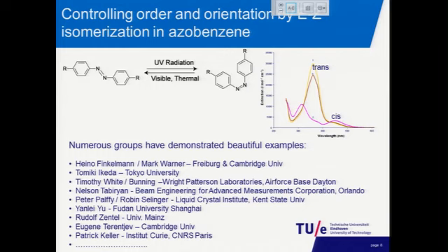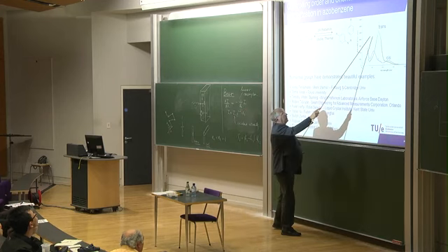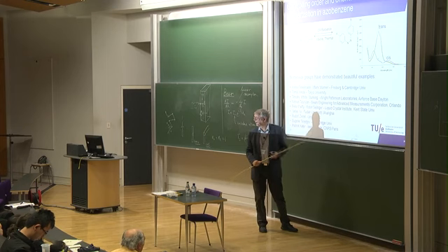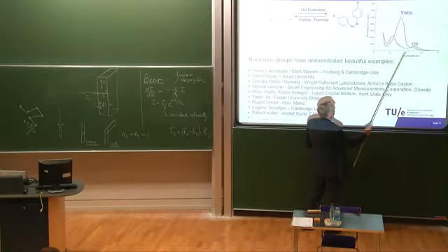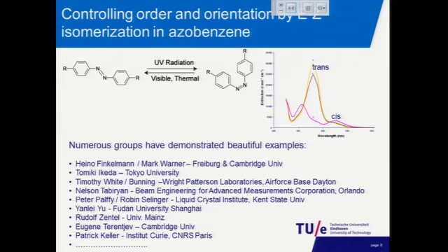If you blend in an azobenzene molecule into the system, then this molecule can undergo a transition from straight to bent. For the chemist, this is just the trans-cis isomerization reaction of this molecule. The trans state has its absorption band around 360 nanometers. The cis state has its absorption band around 450 nanometers. If you excite this molecule in the trans state, it mainly goes to the cis state. If you excite the molecule in the cis state, it goes back to the trans state.